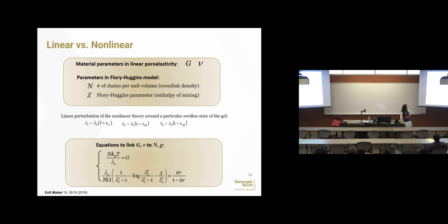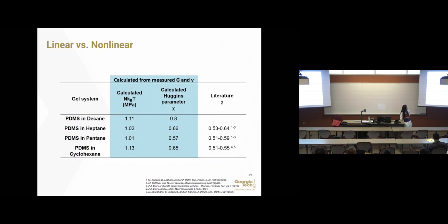And we did a linear perturbation compared with the nonlinear theory. At the end of the day, we get these two algebraic equations, very simple. From the measured shear modulus and Poisson's ratio, we can calculate N and chi. So we did a verification on PDMS swollen in various organic solvent systems. Using the indentation method, we measured shear modulus and Poisson's ratio, and from these we calculate N and chi.